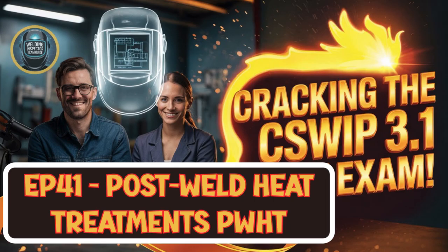Right, you want even heating. Exactly. And also, you need to make sure the fuel itself is clean. Specifically with oil-fired furnaces, you don't want impurities like high sulfur content, which can actually be detrimental to some steels over time. Okay, so furnaces for big stuff. What about the other way, but local?